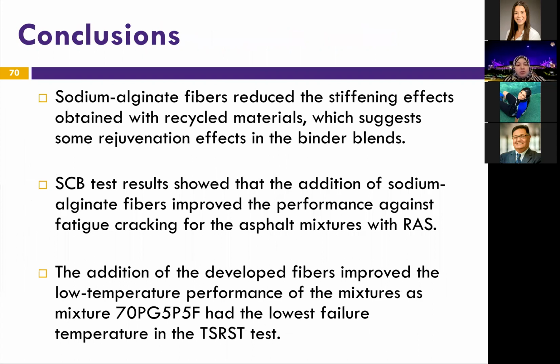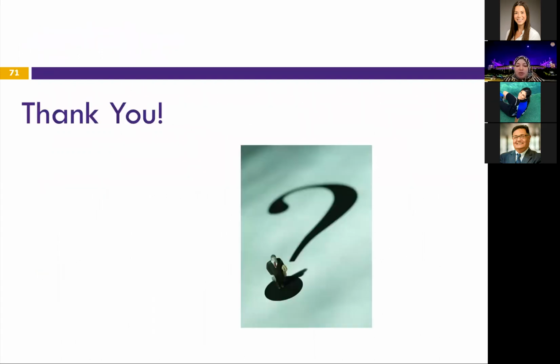So in conclusion, the sodium alginate fiber reduced the stiffness effects obtained with recycled materials, which suggests that the rejuvenation effect is taking place. The SCB test showed that addition of the fibers improved the performance against fatigue cracking. And the addition of the developed fiber improved also the low temperature performance, as we have seen in the TSR-ST test. With that, I conclude my presentation. And I know I am a little bit over time, but we still have time for questions.